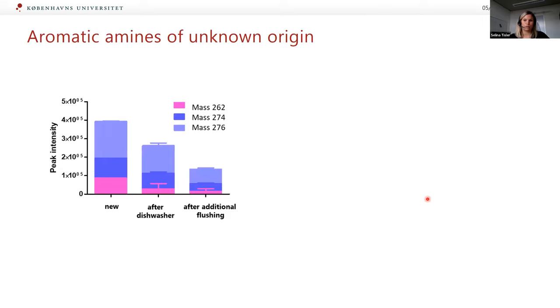Then another compound group we detected were aromatic amines. Here first about the peak intensity. There you can see that they were not removed so nicely after the dishwasher and after additional flushing. And these compounds were among the 10 highest peaks, so peak intensity peaks, we detected in these new bottles, but we could also still detect them in this 1 or 2 year old bottle.